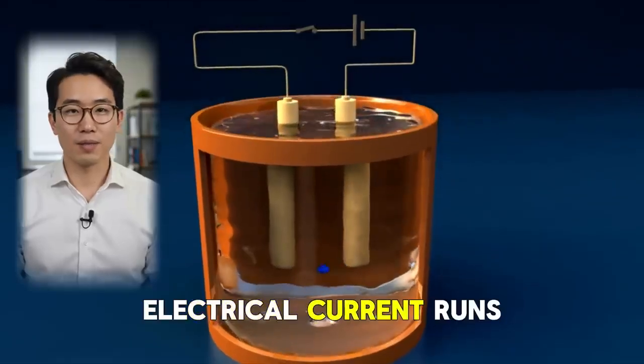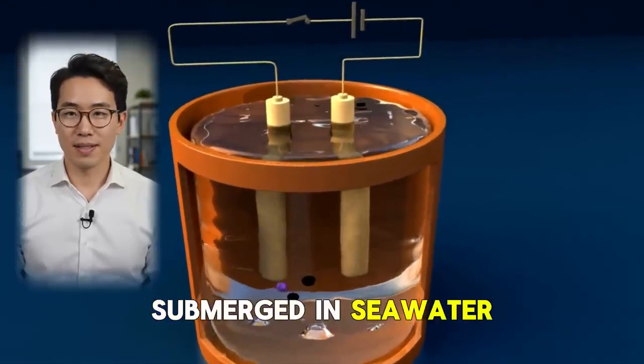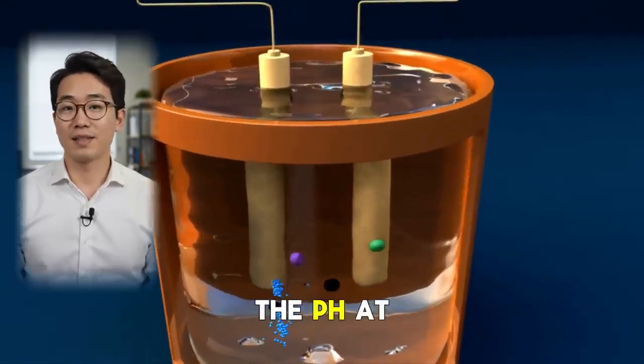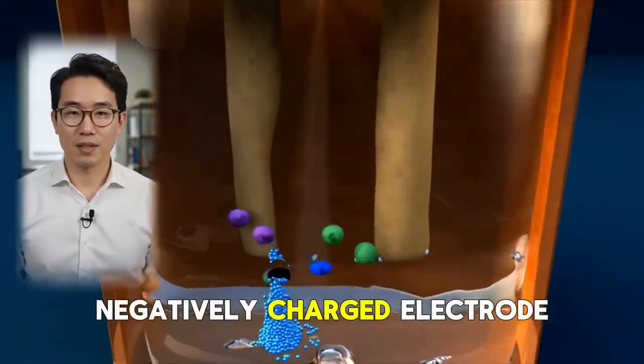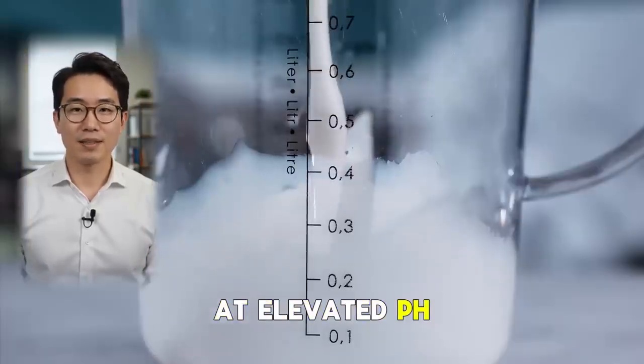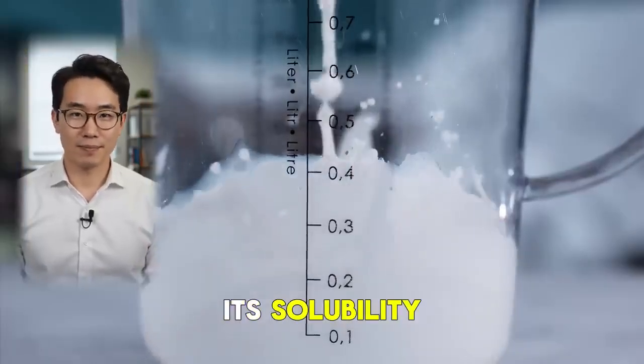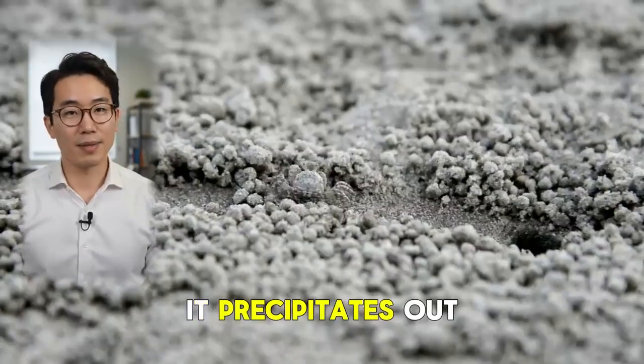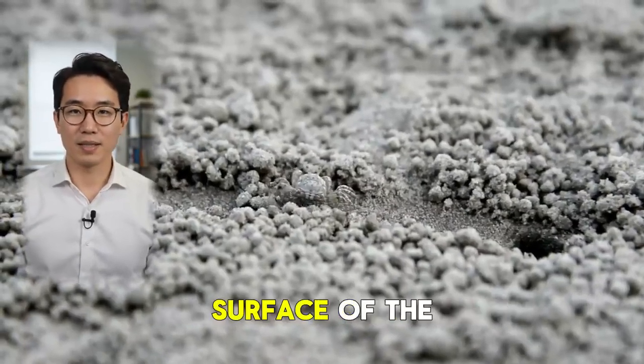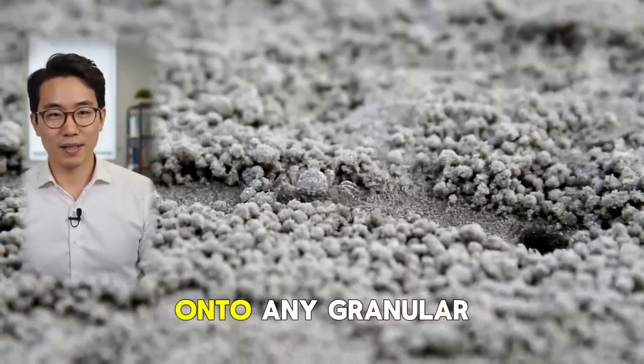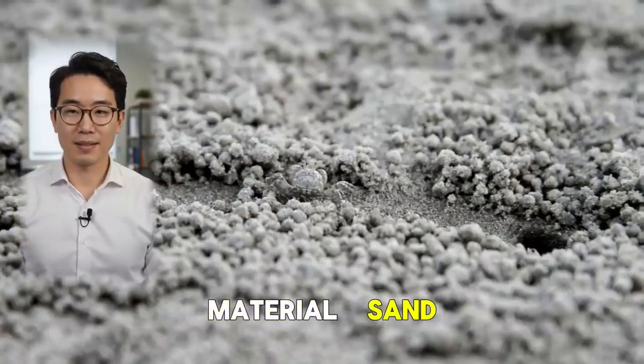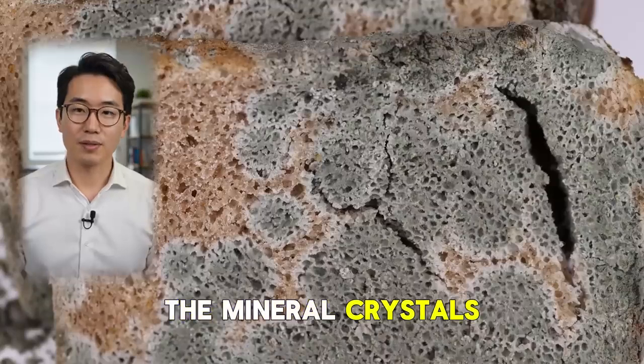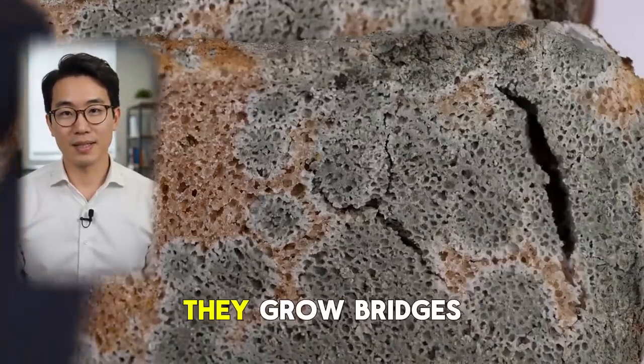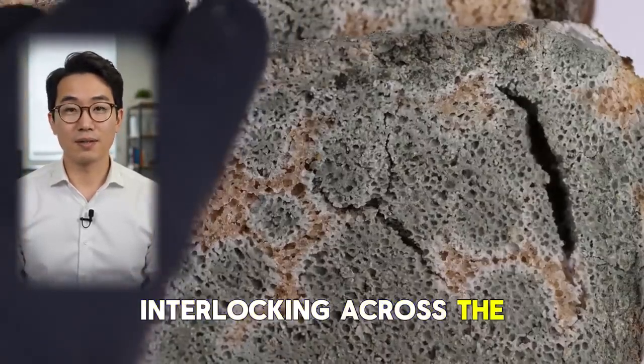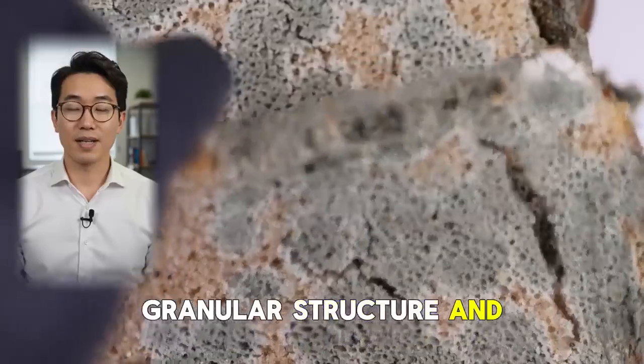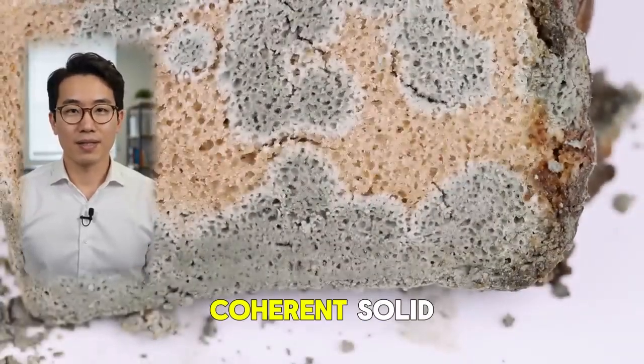When a mild electrical current runs between two electrodes submerged in seawater, it locally raises the pH at the cathode, the negatively charged electrode. At elevated pH, calcium carbonate loses its solubility. It can no longer stay dissolved. It precipitates out of solution and nucleates directly onto the surface of the cathode and, crucially, onto any granular material, sand, in the surrounding zone. The mineral crystals don't just coat the sand grains, they grow bridges between them, interlocking across the void spaces in the granular structure and cementing the entire matrix into a coherent solid.